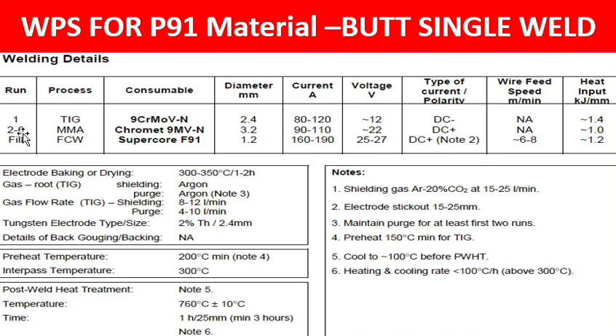Second, runs 2 to 6, it is the fill up. You can say the MMA means SMAW welding. Current is 90 to 110 amperes, and 3.2 mm diameter is required. DC positive is the current polarity. And fill up is FCAW, flux cored arc welding, that is Supercore F91. The diameter of the filler wire is 1.2 mm. Voltage is 25 to 27, and 160 to 190 amperes current. So DC positive also.